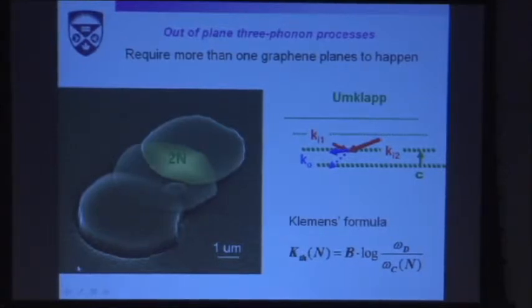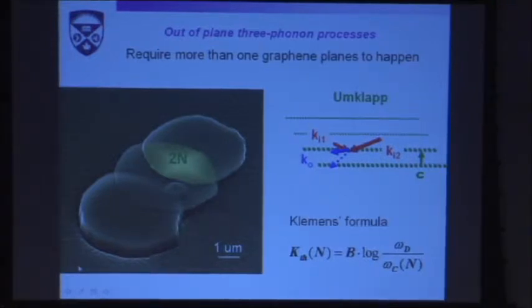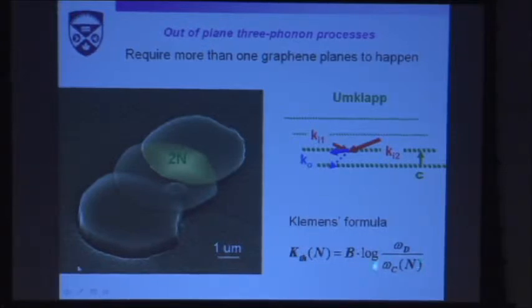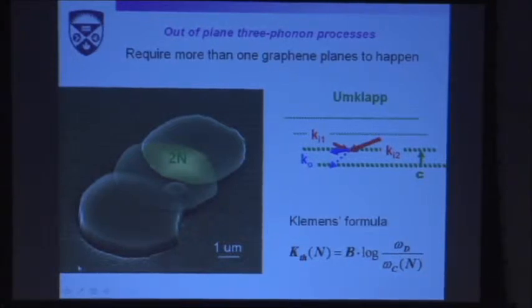And there is a formula that was derived long before graphene became popular. Klemens at UConn, in Connecticut, did these studies just theoretically before and came out with a simple relation that determined the thermal conductivity of these things. It depends on the number of layers. This is the Debye frequency of graphene, a parameter. This is a cutoff frequency for these out-of-plane phonons involved in umklapp processes.